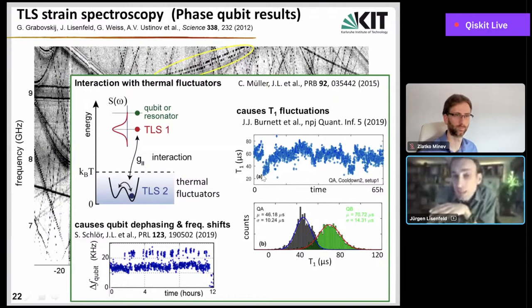However, as I've told you, defects have a very wide distribution of tunneling rates and, of course, of barrier heights. So you always find a distribution of fluctuating defects at different rates and coupling strengths to this defect. And this is much more compatible with such fluctuation data. Yeah?